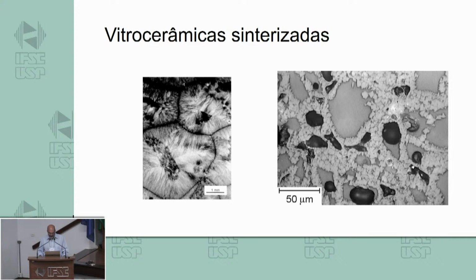The kind of microstructure is more or less this. This is Neoparies, first produced in Japan. This is very nicely densified. You cannot see pores here, and the crystals are needles from the surface. We see here some residual glass, but the system works very well.